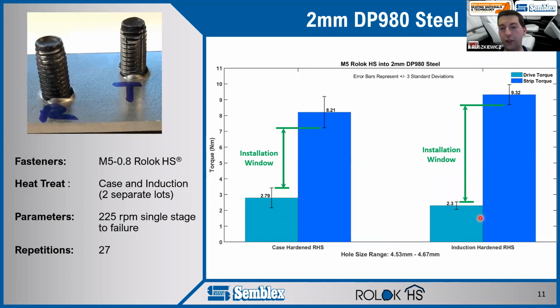But when we compare this to the induction, we see a much bigger window, and there's a couple reasons for that. If you remember that simulation early on, Rolok HS can still deform. It will still drive through even if it deforms. We're simply going to end up shortening and crushing that thread a little bit. And we see that show up as a higher drive torque with higher variance. Obviously, the error bars here are larger, telling us there's more variation than what we got with the induction hardened part. Because those threads got deformed a little bit, we end up with a lower failure torque on the case hardened part than what we have on the induction hardened, which gives us this very large installation window, which works very well.